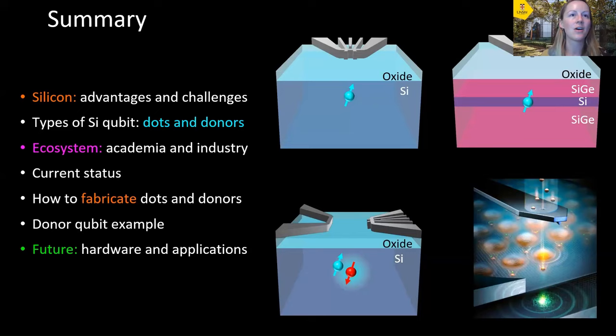For example, you might have the superconducting flux qubit that is nice and easy to fabricate, and you can also operate it with fast gate operations. Then you can couple this superconducting flux qubit to, for example, a bismuth donor that we could implant in silicon nearby to the Josephson junction. This would enable you to harness the long coherence times of the donor system and switch back and forth between these two qubits to harness the best of both worlds.